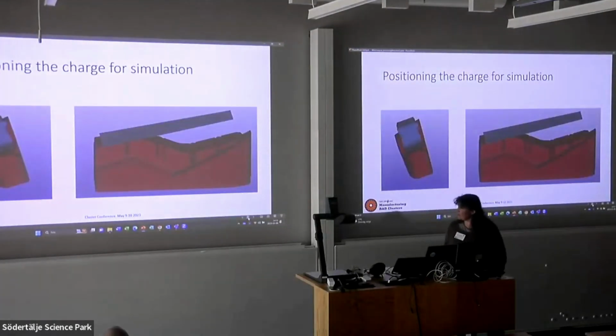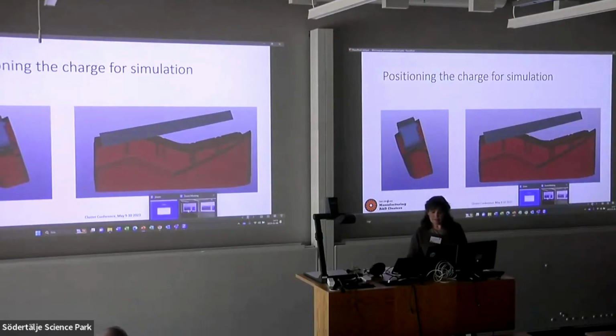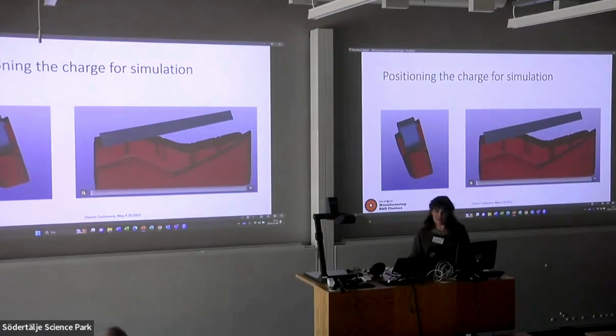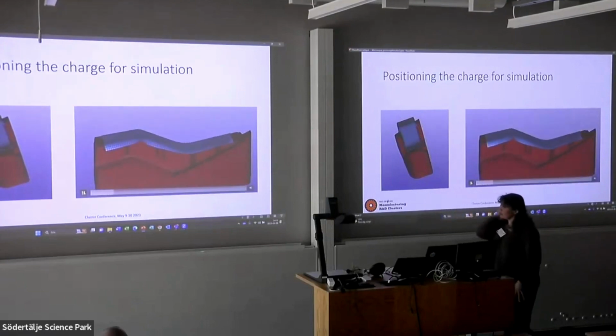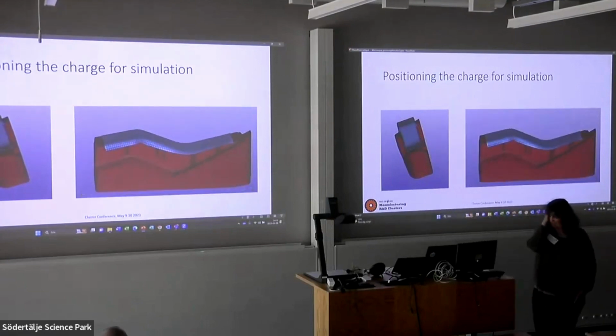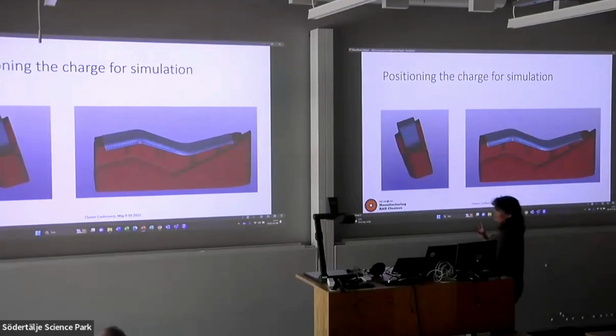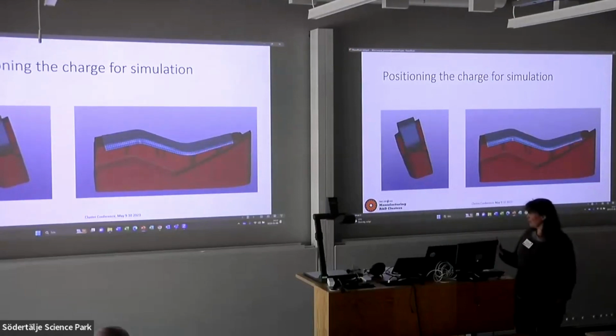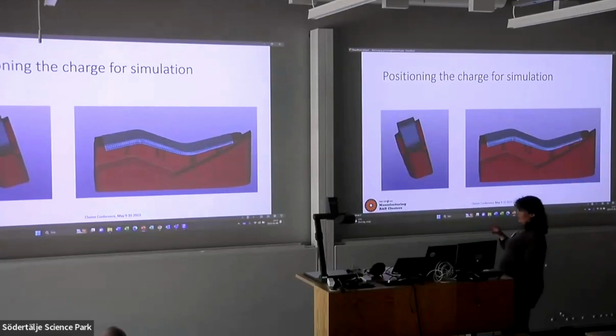One of the really important things that we found was getting the charge in the right place. So this was done really, really simply with LS-DYNA, and it made a big difference to the results that we can get from the commercial software. So if we can get the charge to be in the right place at the start, then we get much better results from the software. So I think this was a key element in getting it right.